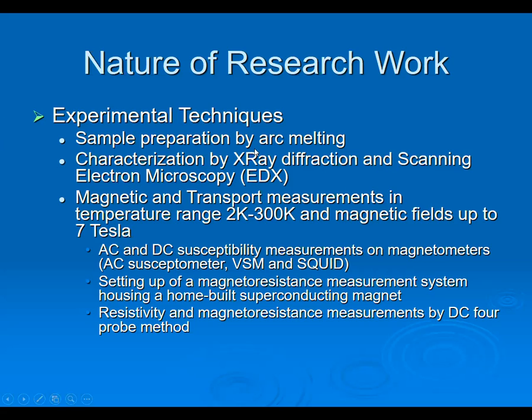And we looked at magnetic and transport measurements. So the range of temperatures between 2 Kelvin to 300 Kelvin, which means that you are going to low temperatures and the coolant which is being used is liquid helium. And liquid helium alone would not be enough. Most of the older cryostats used to have an outer nitrogen shield. This was essentially because you can at least reduce the usage of liquid helium and reduce the boil off, since nitrogen is still cheaper than liquid helium. And the magnetic fields up to 7 Tesla.